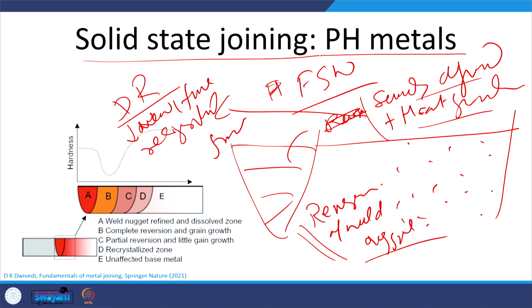So, due to the dissolution of the precipitates, obviously there is some effect of the elements that are going into solution, maybe in the form of solid solution strengthening, but since these are precipitation hardening metals, there will be a drop in hardness and strength. That is what we can see in the weld nugget: there is a drop as compared to the base metal, a drop in hardness and strength, and this is attributed to the loss of precipitates.